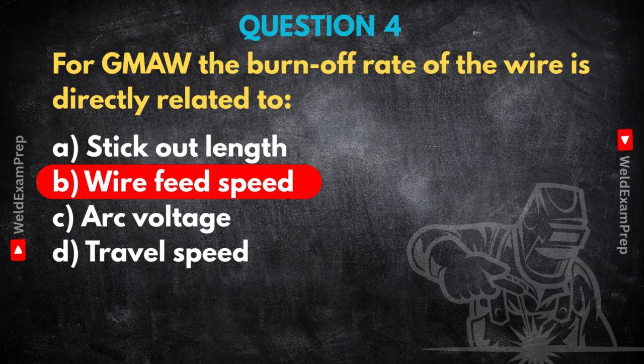If the wire feed speed is way too high for the voltage setting, the wire literally stubs out into the weld pool, jabbing into it. Yeah, it causes a really unstable arc, loads of spatter, and you risk lack of fusion because the arc isn't burning properly. Visually, you might see a narrow, kind of humped up bead, maybe poor wetting at the edges.